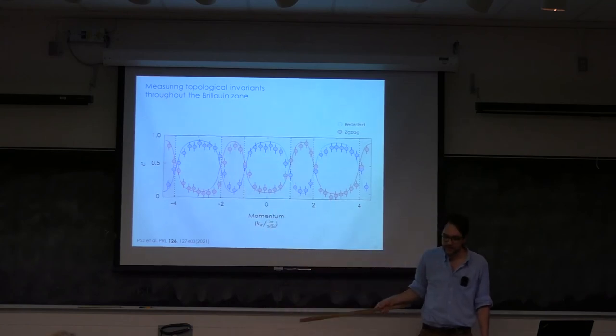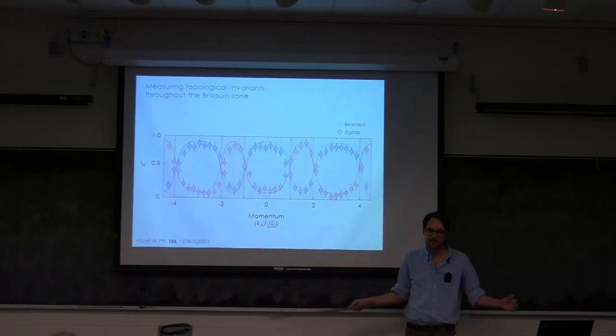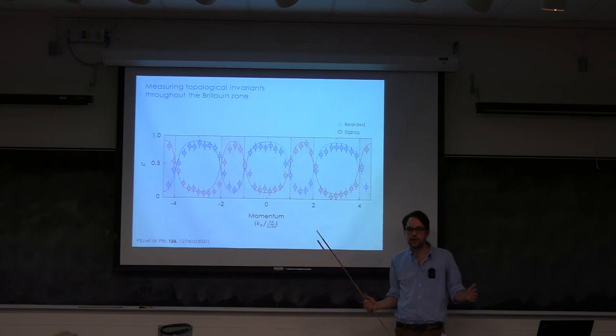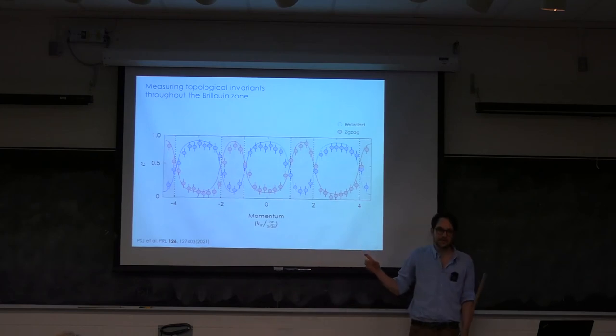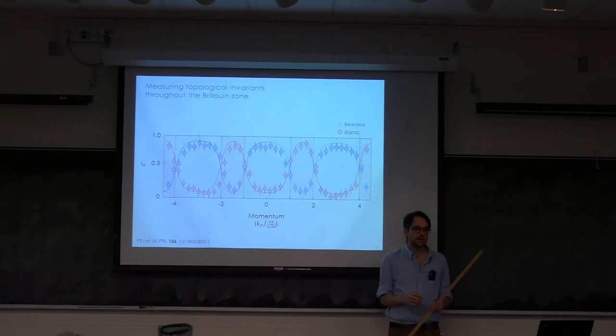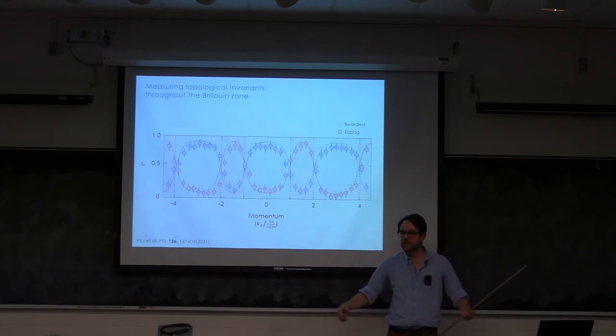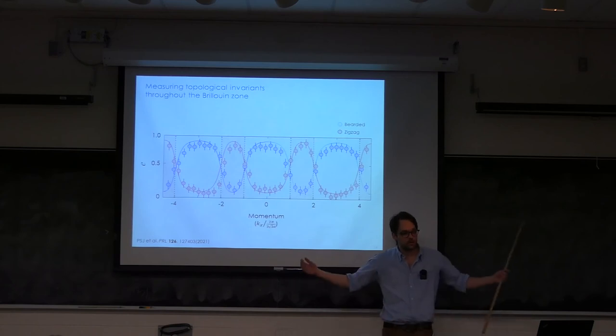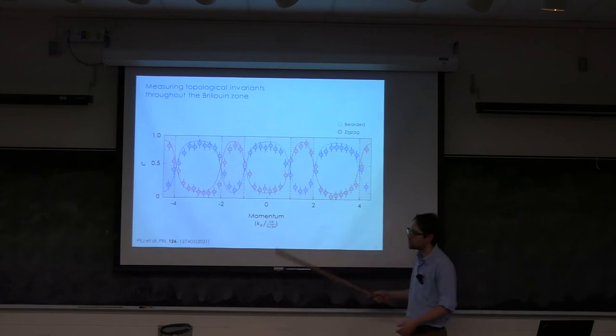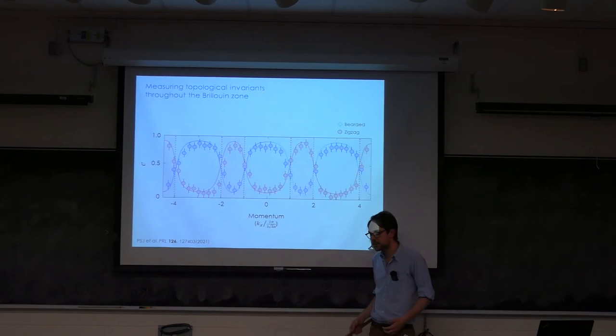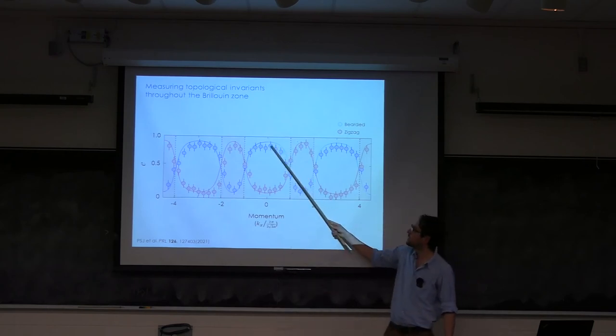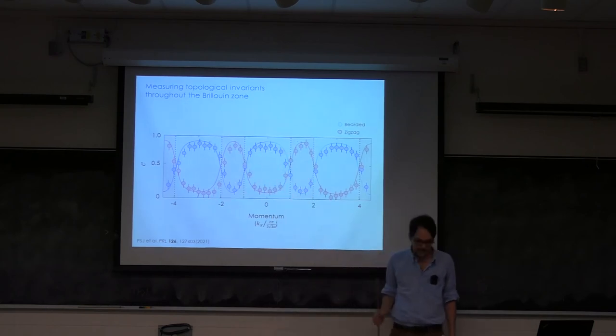And this comes from the fact that the argument relies on reaching thermodynamic equilibrium. And the problem is that in these two-dimensional lattices, the quality factor is much lower than in our one-dimensional lattice because they're more difficult to fabricate. So the photon stays there on a much shorter time scale, and the wave packet doesn't have time to spread over the lattice. So it doesn't exactly go. But provided that we were building better lattices, which is really difficult, we should have something. But we still capture this idea.